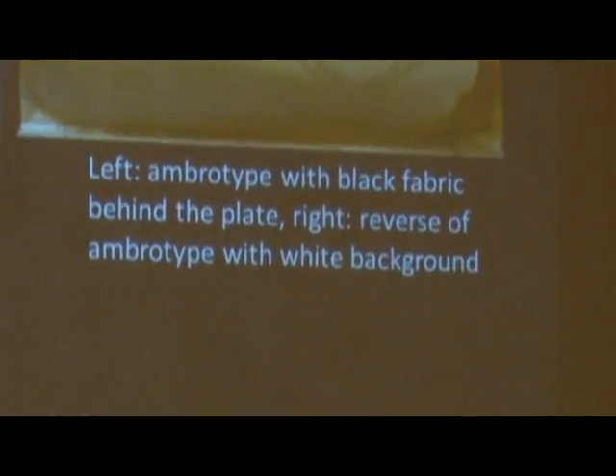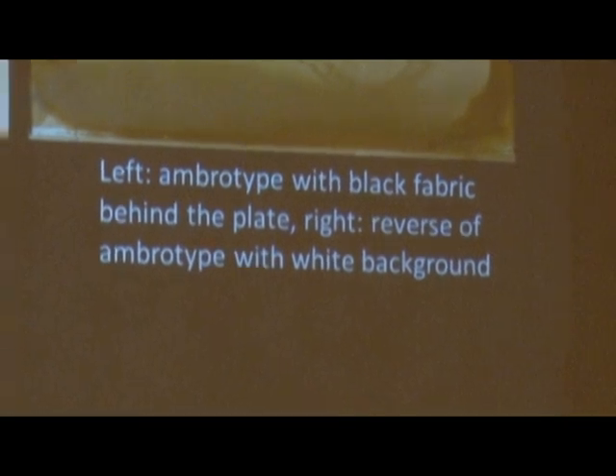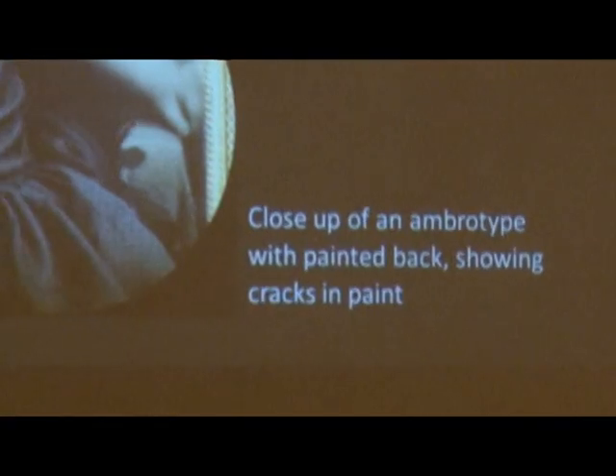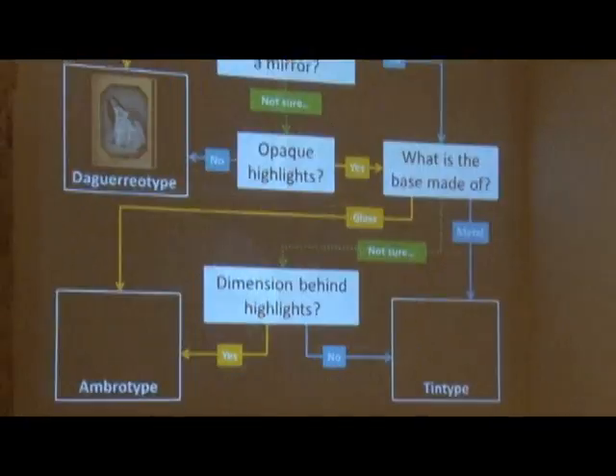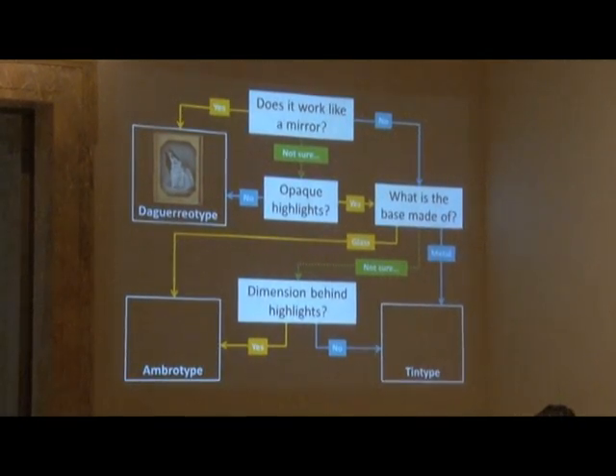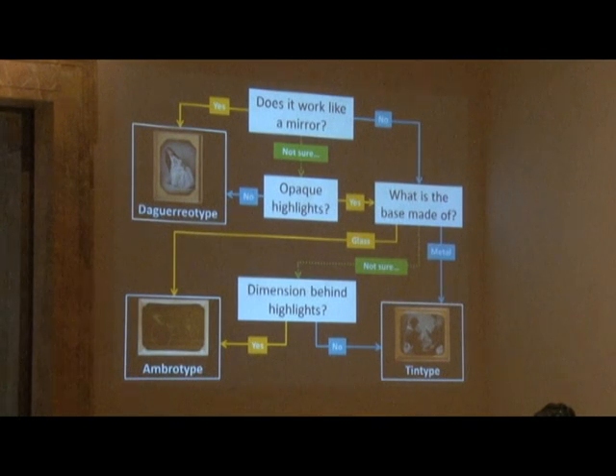That is because ambrotypes bear only highlights on the glass, like the image on the top. They're the same plate. The right is the ambrotype without a black background. Unless the ambrotype is made on colored glass, the rest is clear. And the black is provided by a piece of black paper or fabric behind the glass on the opposite side of the white image material. So that's why there would be a little gap. Or sometimes the back side of the glass is painted black. In that case, you often see little cracks in the paint, and you can see the crack formation under the image. I have some tintypes here too, so you can experiment with that. Okay, so the dimension behind highlight, that was the ambrotype, and that's the tintype.